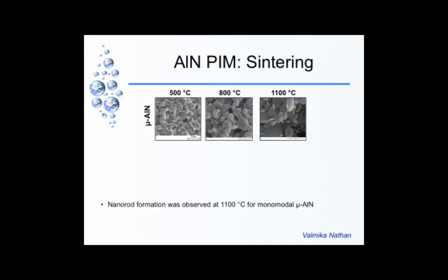So this is just a microscale aluminum nitride. We added yttrium oxide, to form a liquid phase. You know that alumina and yttria form a glass. So we used about 5% yttria. The yttria we used were nanoparticles. One thing about nanoparticles is, as you reduce the size, it turned out that the melting point gets depressed because of the increased surface activity. So when you push the materials to the nanoscale, the liquid forms at a lower temperature.